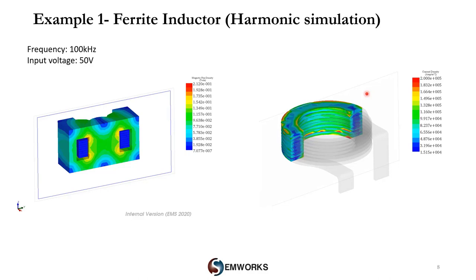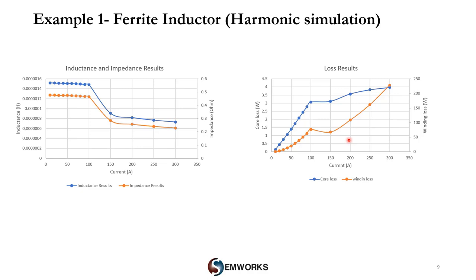In the left figure we can see the inductance results versus current — it confirms that the inductor can provide high rated current performance. The inductance is constant up to 150 amps, then it decreases suddenly when the core reaches saturation. Next, a frequency-domain simulation is performed using the AC magnetic solver of EMS with an input voltage of 50 volts at 100 kHz. The magnetic flux results show hot-spot regions around the core windows, and the current density results show skin and proximity effects caused by the high-frequency signal.